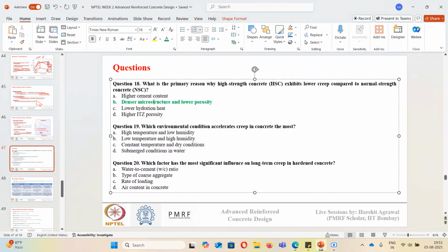For question number 19, I am getting answer as A. Which environmental condition will accelerate creep in concrete the most? Okay, so the more the drying effect, or the more the exposure to a certain condition where along with sustained loading there can be moisture loss, there can be cracking inside the concrete, the more will be the creep. So that's why we have high temperature and low humidity as the most critical condition to accelerate creep.